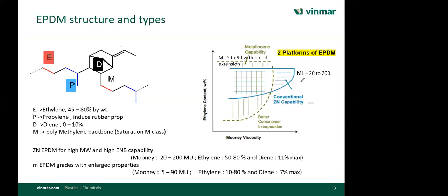The metallocene is the newer version of the solution polymerization catalyst, and it has a much faster productivity rate. So the product price should be cheaper compared to the Ziegler-Natta catalyst system. So most of the new plants are coming in metallocene. With metallocene, we get a broader range of Mooney. In the lower segment, the Mooney can start from 5, but again, we cannot exceed Mooney beyond 90. So if you see the grades of EPDM from all the metallocene producers, you will find maximum Mooney 90.